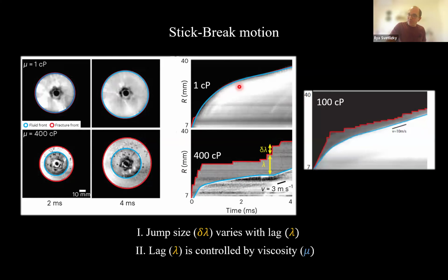And just to fill up the gap, this is an intermediate example with 100 centipoise. And what you see is that the jump size, delta lambda, increases with increasing lag. And the lag by itself increases when you increase the viscosity of the fluid you're injecting.